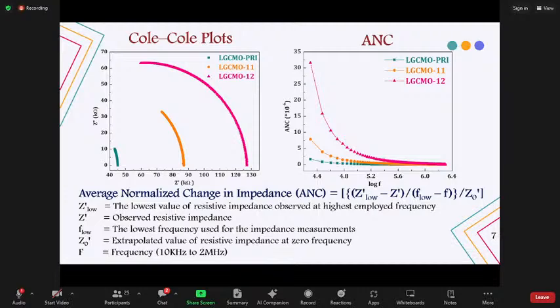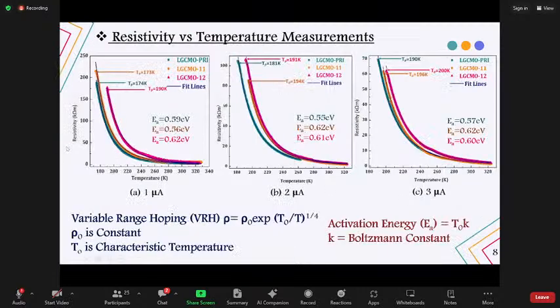For the different currents employed, that is 1 microampere, 2 microampere, and 3 microampere, we can see that as the temperature increases, the value of the resistance decreases for all the graphs under study. From this, we can see that all the prepared samples possess semiconducting nature. And from this graph, by increasing the value of the current, we can clearly see that the TP is shifting towards room temperature.